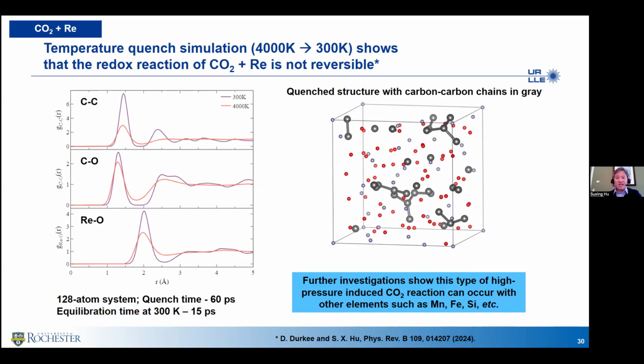It turns out this reaction is irreversible. Once the rhenium facilitates the dissociation of the CO2 molecule at this high temperature and high pressure, even if you quench that down to room temperature, the CO2 does not come back. So that's a good sign. It means if you do it this way, you will permanently destroy CO2.